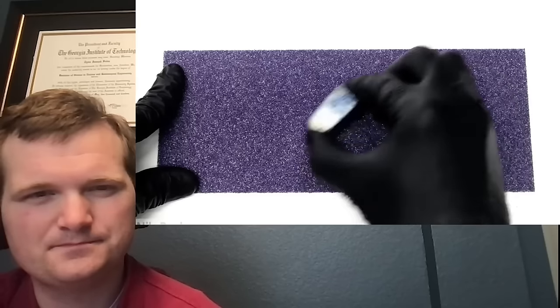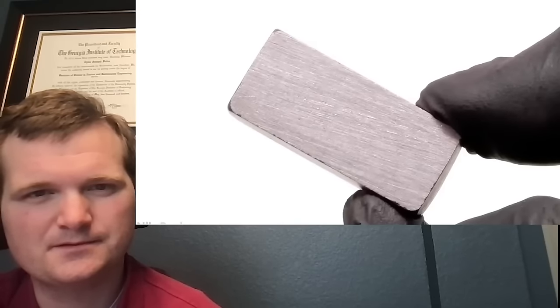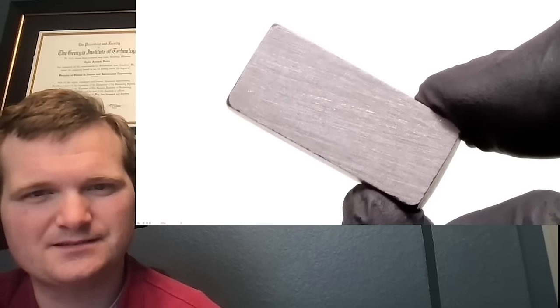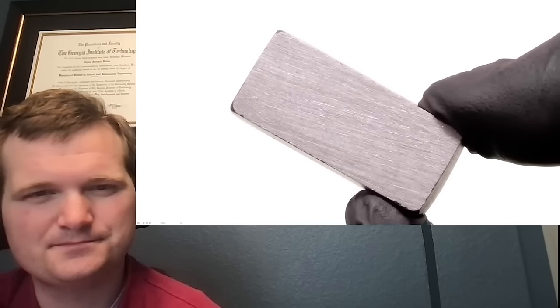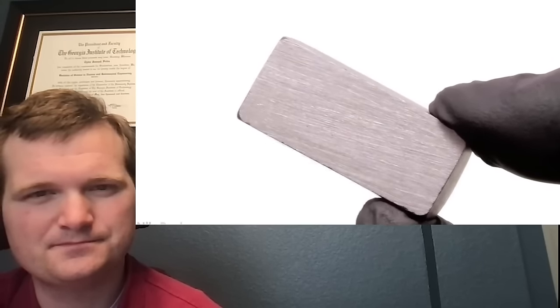Almost immediately, it was already pretty clear that there was a major improvement, and even after very little sanding, it looked like most of the cracks were gone. Nice. I would only really be able to know for sure once it was all nice and shiny, though, so I just kept on going, and many horribly painful hours later, I annealed it, and this was what I eventually had. Whoa. Without even comparing it to the other bar, this one was clearly way better, and what I was extremely happy to see was that it didn't seem to be riddled with a bunch of small holes.